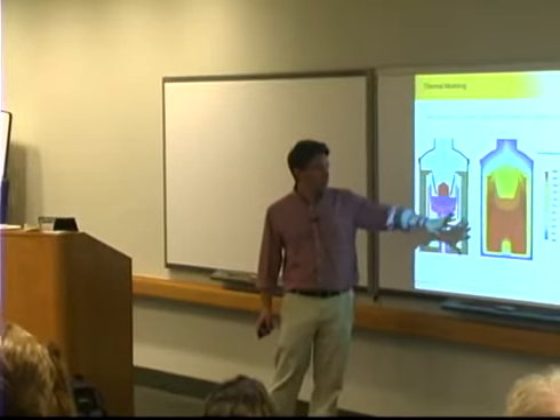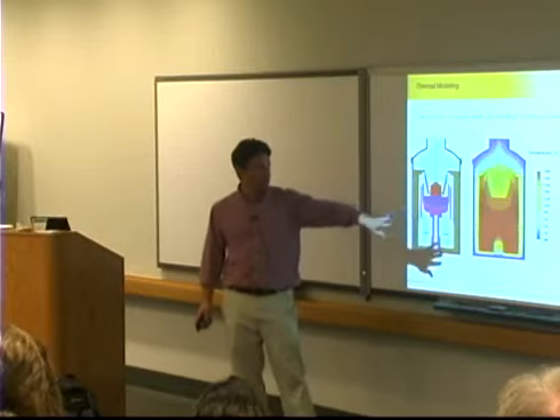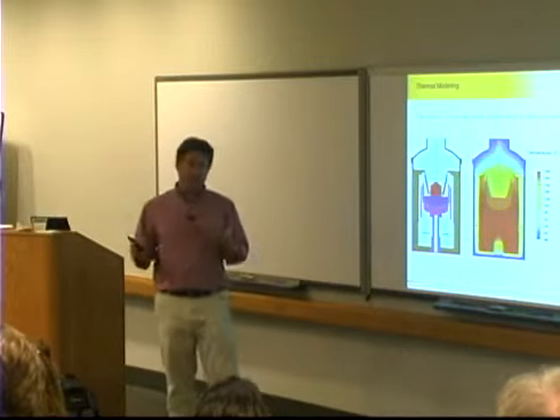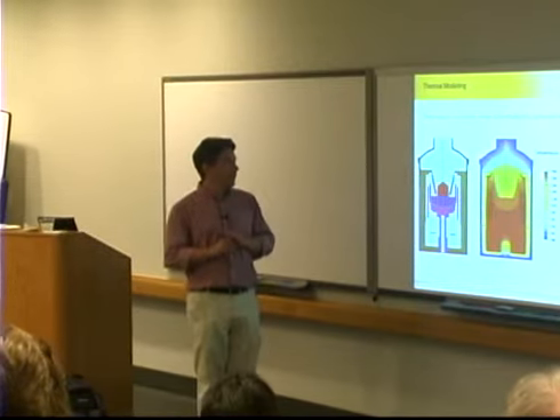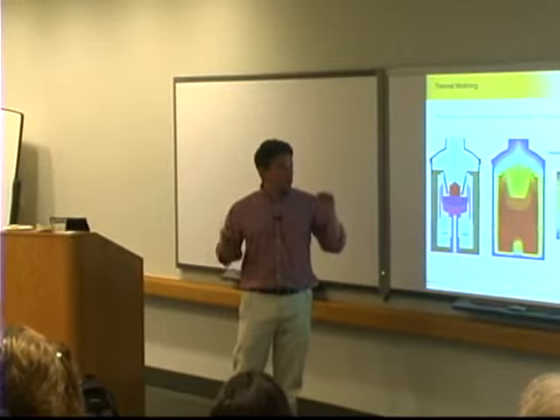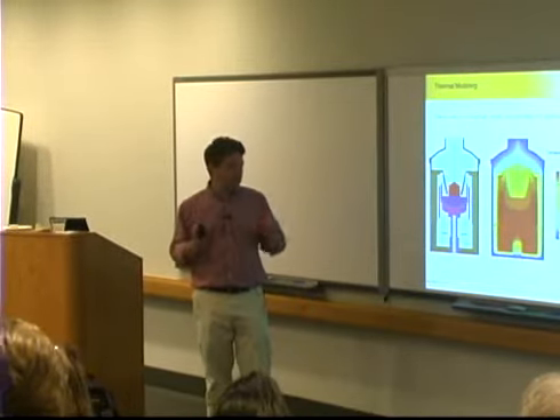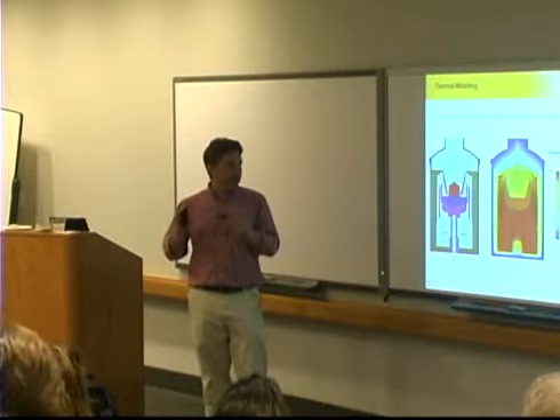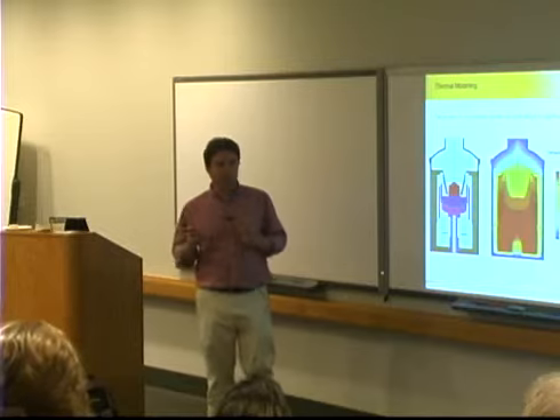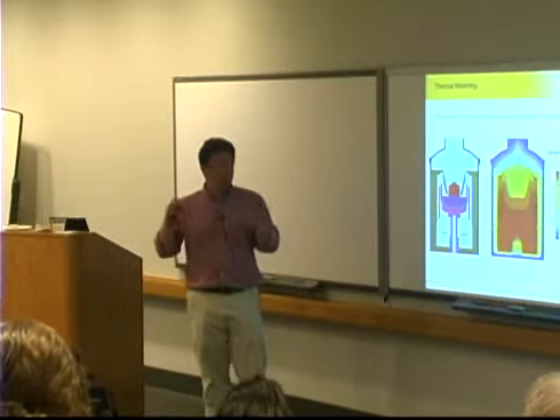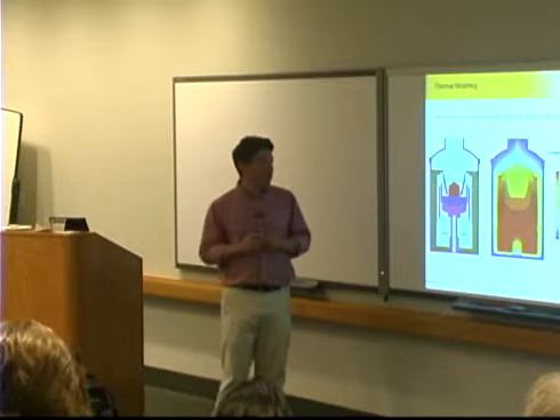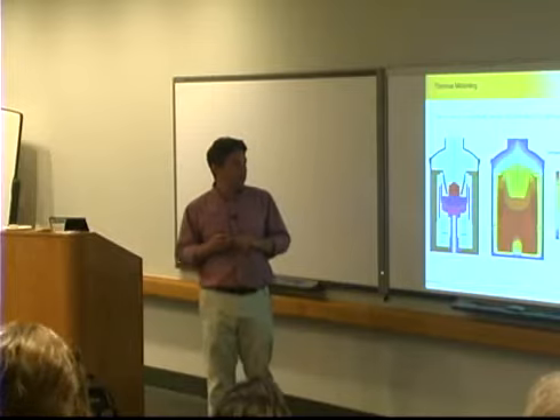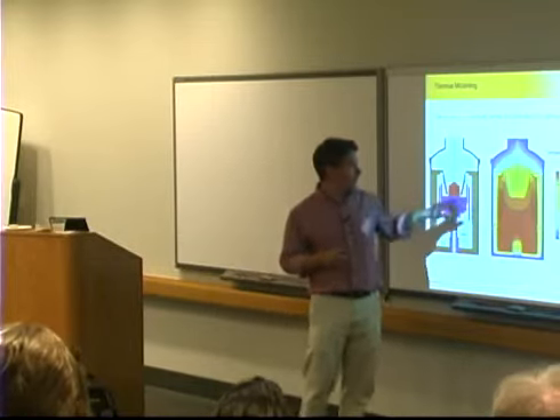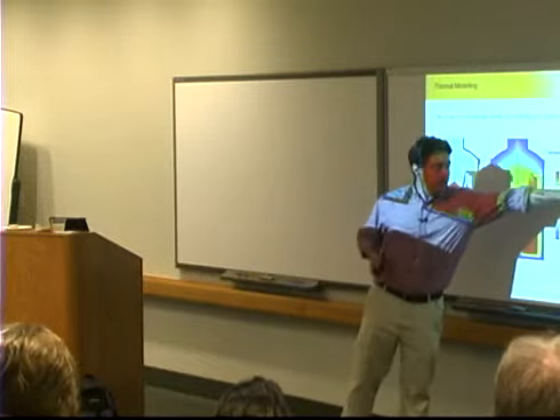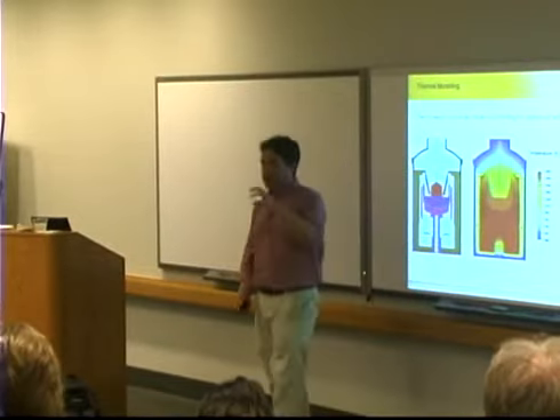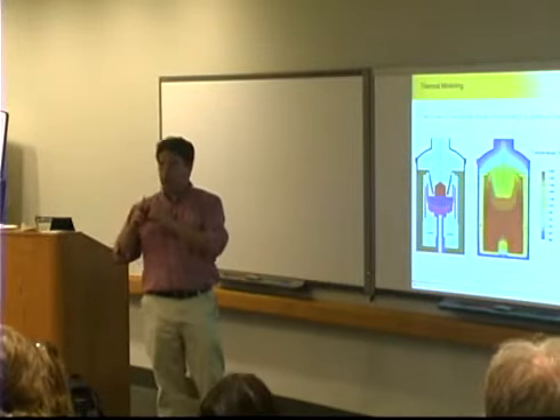There's been a lot of work, just hundreds of papers, that have gone into thermal simulations and convective simulations and magnetic. Really every side of this thing has been looked at. And still you can't really run a control program that is really in control of the whole thing. It runs in feedback, and there's a little bit of positive feedback, I think, where you have to really oversteer it to keep it in diameter control. So they do a pretty good job with that. But the bottom line is that you're still growing around 1 millimeter per minute, and you're growing just one ingot at a time, and that ingot has just one wafer cross section in it.